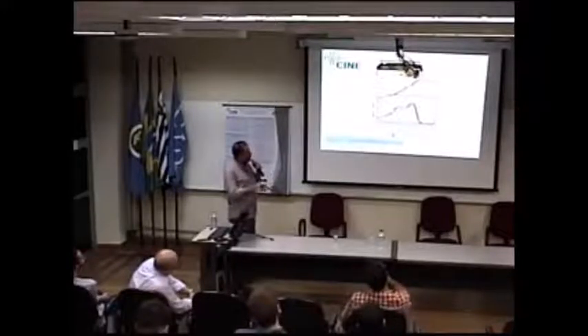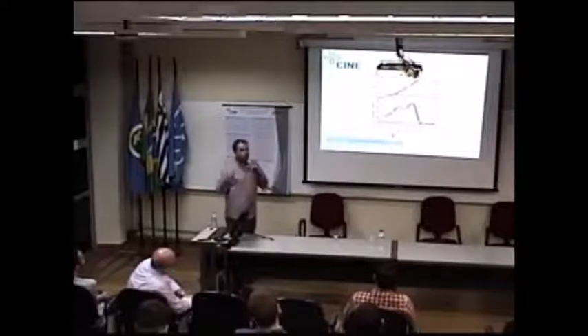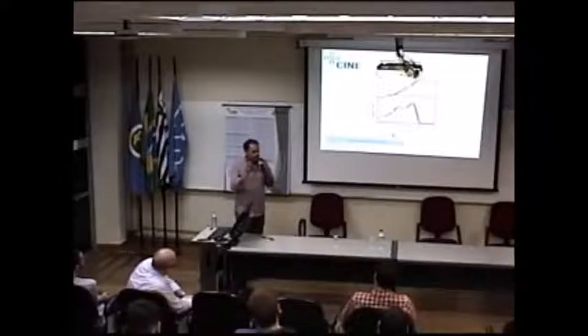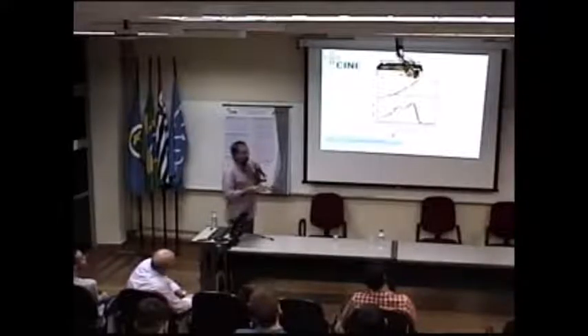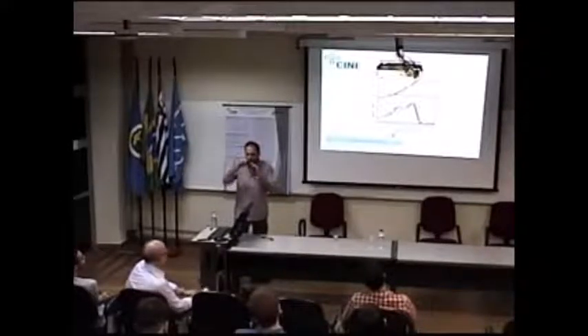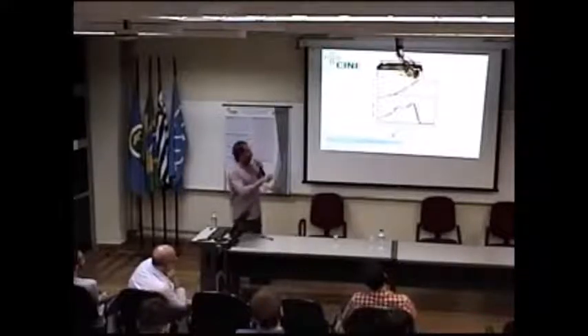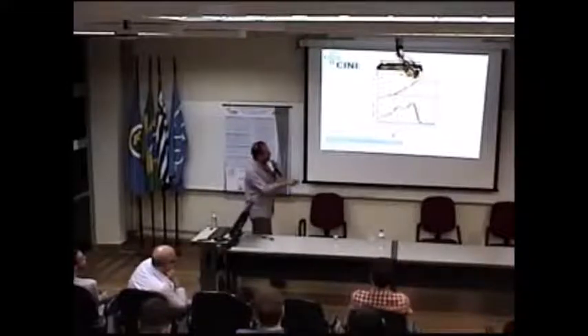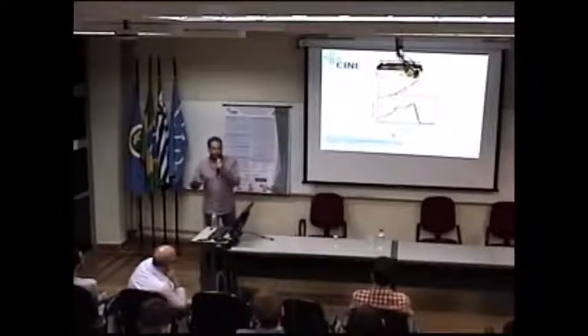Those are the solid state diffusion processes going on in those materials, and we activate different ones. The nanorods have a very defective surface, very high surface area, and a lot of defects, so they're willing to move. Those are the defects that move when you increase the temperature. On the other hand, the cubes have very controlled faces of the crystals, very low energy. So when you put them together and increase the temperature, at the end of the day, really nothing happens. They stay rather porous, even at 1,400 degrees C, which is very cool for catalysis if you think about it.